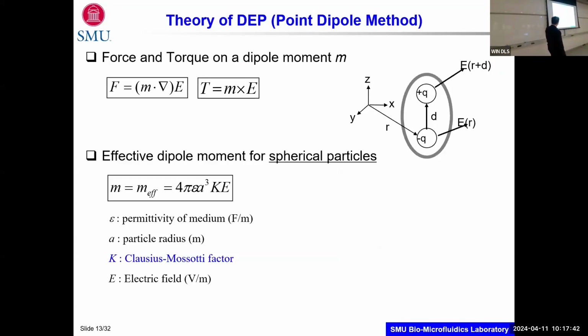So why does this happen? It happens because these are polarizable particles, and there is a dipole moment that will create a force and a torque. In the simplistic form, there is the point dipole method. There are other methodologies, of course; the Maxwell stress tensor method can be used as well, but that's more thorough. I like simple things, but even this is kind of complex for me. So basically, you can have a dipole moment for spherical particles given by this formula, where a is the particle radius, E is the electric field, and K is the Clausius-Mossotti factor. This is actually the key that's going to determine whether you will have a positive or negative dielectrophoresis.